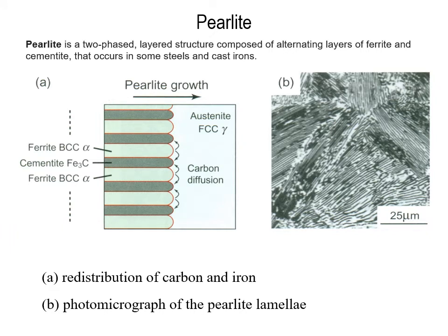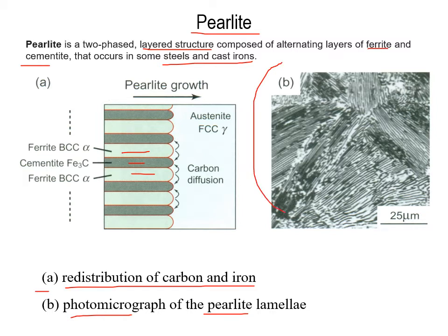So what is pearlite? Pearlite is a two-phase layered structure composed of alternating layers of ferrite and cementite. This occurs in some steels and cast irons. We can see here in our diagrams, in diagram A, these different layers, and this shows the redistribution of carbon in iron. And in B, we have a photomicrograph of the pearlite that we can see in this image here. And we note the scale down at the bottom of 25 microns.